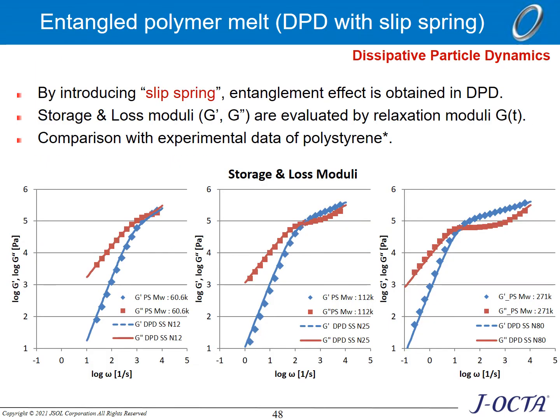Recently, it has become possible to simulate entangled polymers using dissipative particle dynamics. In general DPD calculations, the entanglement effect does not occur because the molecular chains slip through each other. Therefore, a virtual chemical bond called slip spring is introduced to obtain the entanglement effect. Here, we evaluated the G' and G'' of polystyrene from the relaxation modulus. When compared to experimental results, good agreement was obtained for each molecular weight.